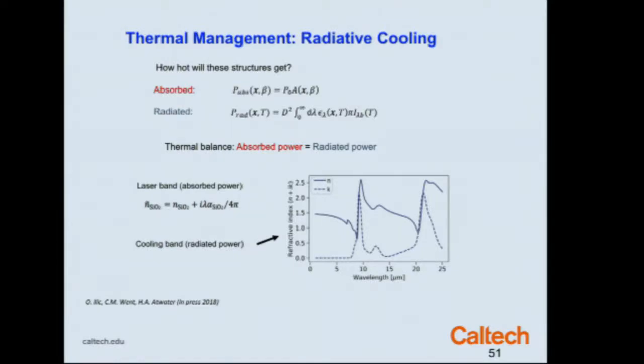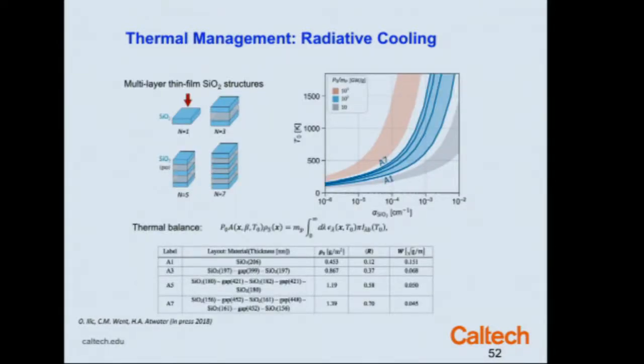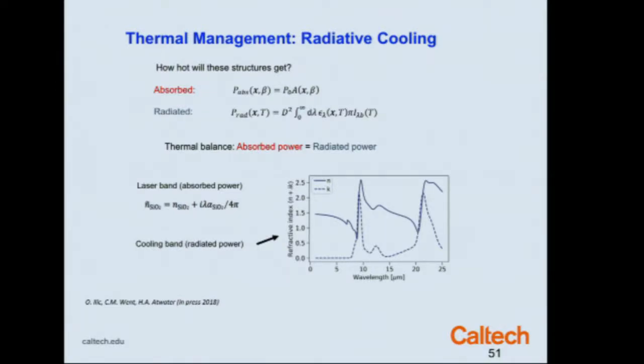So thermal management. I mentioned in order to do thermal management, I have to have some emissivity. And so, for example, in the case where I have a light sail that is made out of a dielectric material that has phonon polaritons in the 10 micron or 10 to 20 micron range, I have now some absorption and therefore some emission of light and radiation at this wavelength. And so what we found was that by making laminates, say, of a highly reflective material at pump wavelength like silicon, and silicon dioxide, which is transparent at the pump wavelength, but which has these phonon polariton or Reststrahlen bands. This, in fact, is the refractive index and absorption for silicon dioxide around 10 microns. Many of you may know, if you've ever shined a long wavelength laser, silicon dioxide, which is transparent in the visible, is opaque at 10 microns.